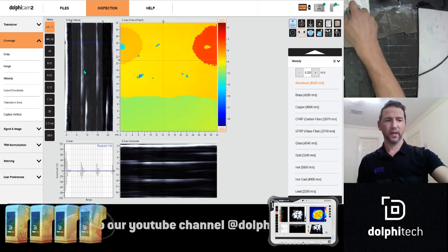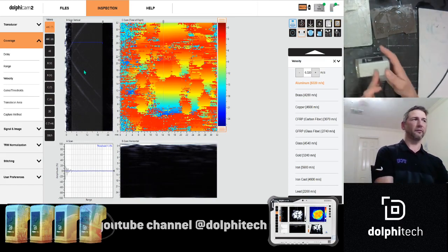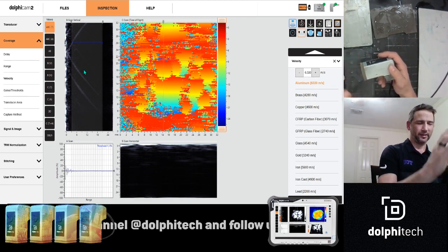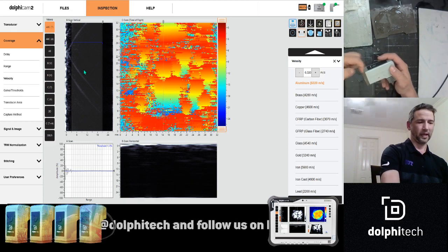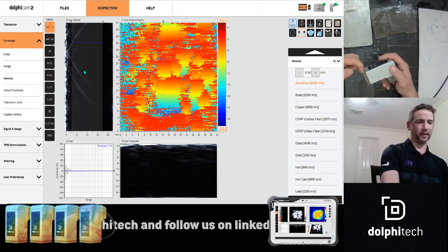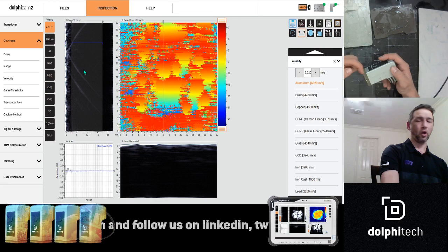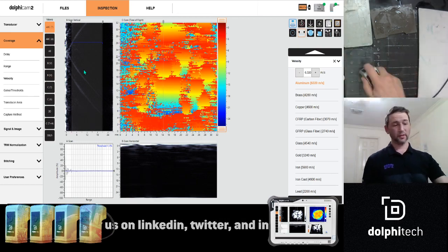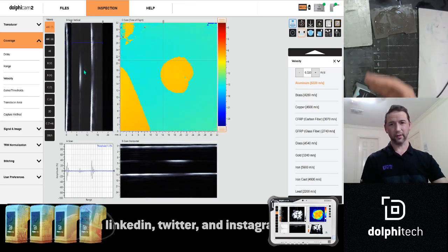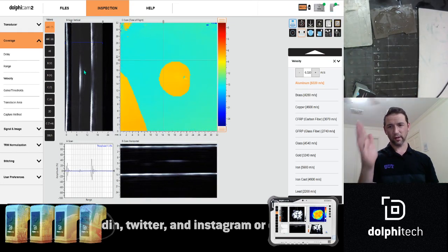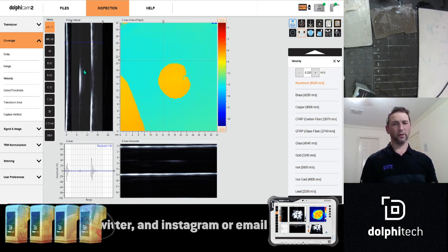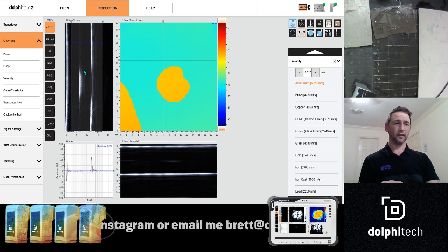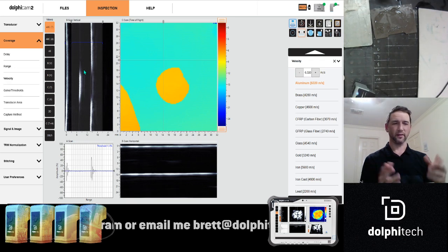The reason why is because our TRMs are fully digital, so it's giving us a little bit of flexibility. We're calibrated, or normalized, to the delay material, the delay line right here. We know exactly how long that sound path is, so we can calibrate to that. Then when we go on to our material, we know the given material that we're inspecting, and we should know exactly where our start is and where the end is. So if it's 18 millimeters, 17 millimeters, then we know our back wall is appropriately there. And then we coordinate that to the other indications that are on that calibration block.